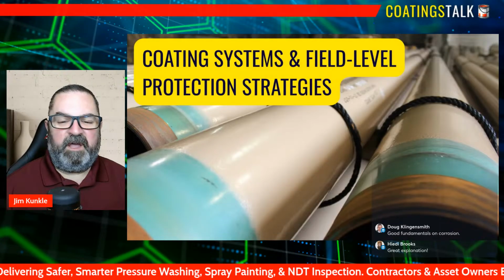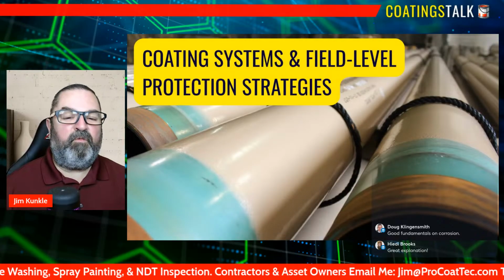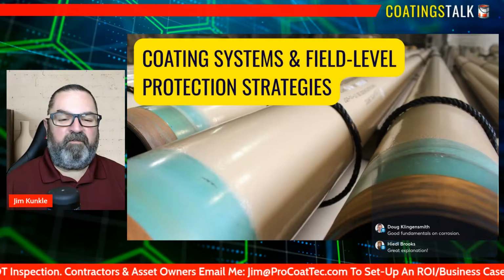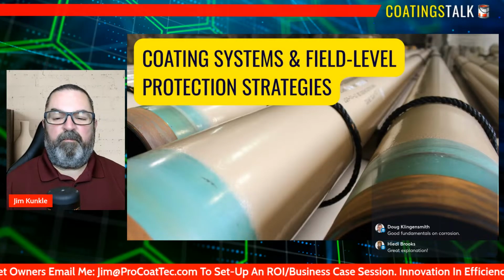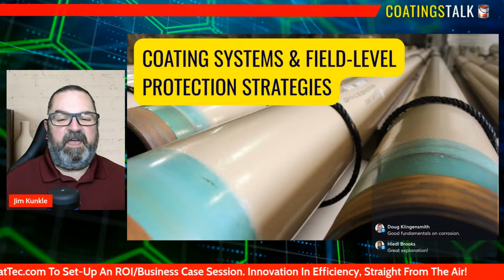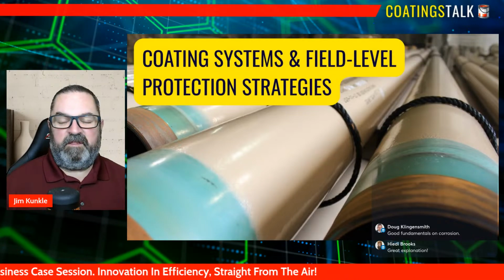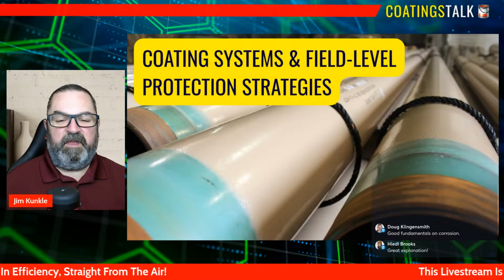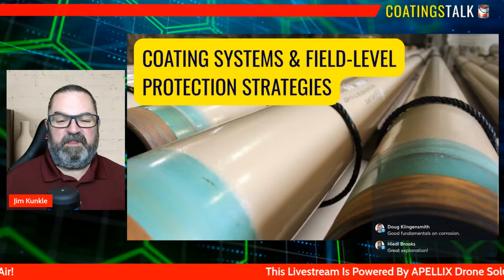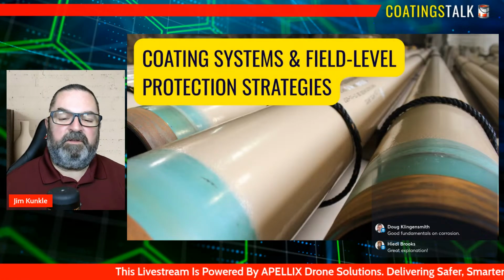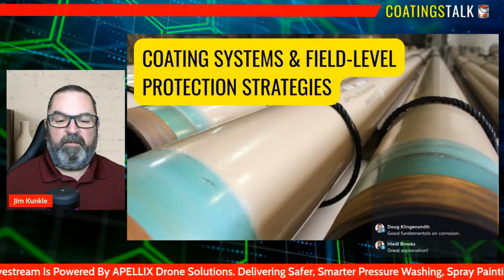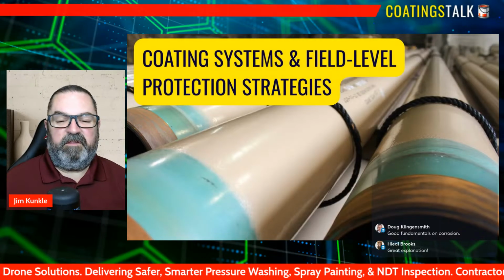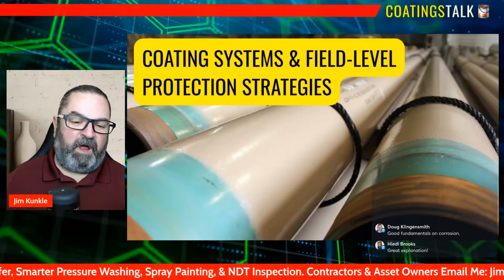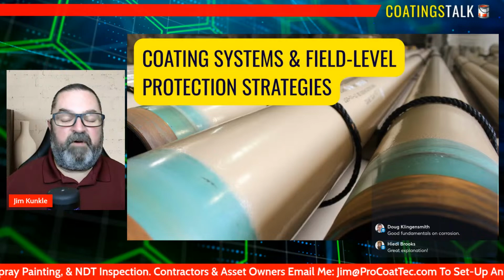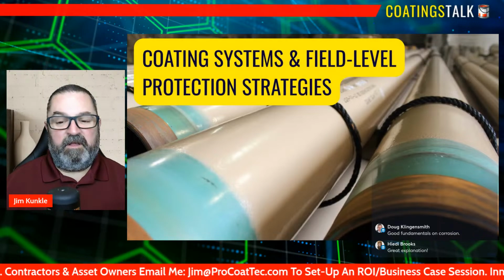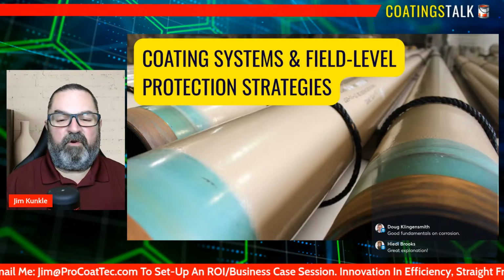Beyond the simple barrier protection, many modern coatings incorporate active corrosion control mechanisms. Zinc-rich primers, for example, provide sacrificial protection by corroding preferentially to steel, effectively taking the hit and preventing galvanic corrosion from attacking the substrate. Other coatings contain corrosion inhibitors that neutralize contaminants or slow down chemical reactions at the metal surface. Some systems are engineered to resist specific threats like chlorides in coastal environments or acids in industrial settings. When these systems are applied correctly, they don't just delay corrosion, they fundamentally change the environment at the metal interface, making it less likely for corrosion cells to form.